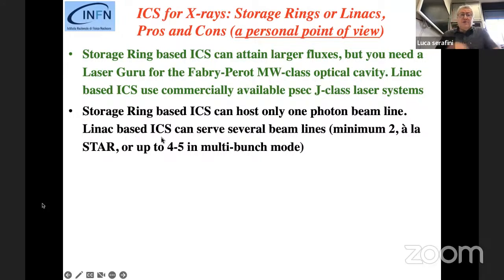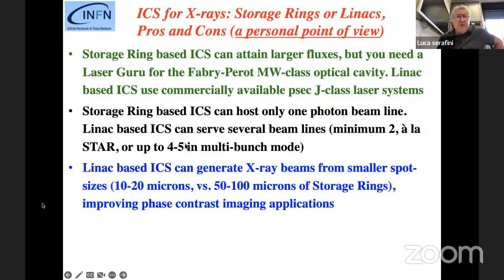While in LINAC-based inverse Compton scattering sources, you can operate several beam lines. At STAR, we have 2 beam lines that in single bunch mode will be operated alternatively, 50 Hertz each of the 100 Hertz repetition rate. But you can certainly operate, going to multi-bunch mode, the LINAC-based ICS with several beam lines simultaneously. This is simply due to the physics of ICS. The laser pulse is transparent to the electron beam, so you can focus and refocus quite a number of times. And this was also demonstrated experimentally in the context of ELI-NP and the gamma beam system designed and proposed by the EuroGammaS European collaboration.